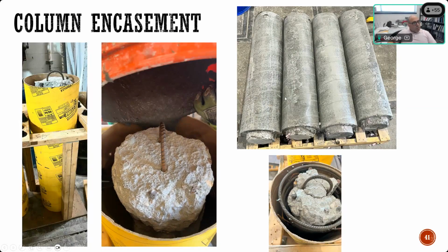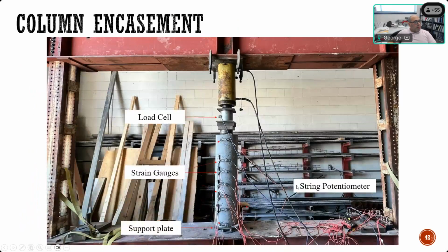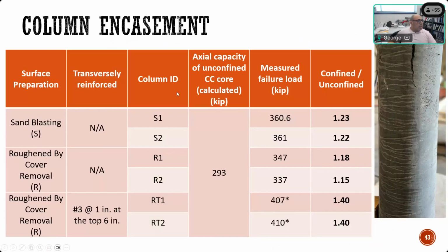Some specimens were done with sandblasting surface preparation, others with removing the cover. In some cases, we added additional confinement reinforcement. So to look at how this will perform when we apply axial load, to see how much increase in the capacity we get, here's a summary of the results that we looked at. We looked at 2 specimens with sandblasting surface preparation, others with removing the cover, and 2 of them were adding also additional tie reinforcement at the top.